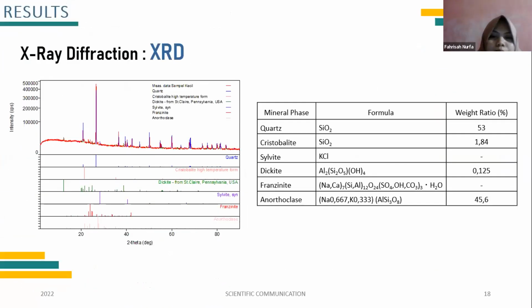Next is XRD results. We get the graph of the intensity against 2 theta. It can be seen that there are intensity peaks in the graph that can provide the type of mineral phase of the sample based on the XRD database used. There were 6 mineral phases detected, namely quartz, cristobalite, sylvite, dickite, franzinite, and anorthoclase. Each phase has a formula and a weight ratio, but weight ratios do not exist for sylvite and franzinite due to the limitations in the XRD database.